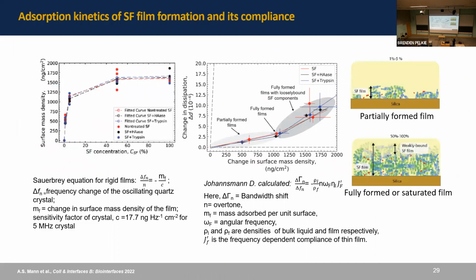So here are some results from that study. We used the Sauerbrey equation for rigid films to convert the changes in frequency to surface mass density of hydrated adsorbed mass. If we plot that as a function of bulk concentration of synovial fluid, then we get a Langmuir isotherm. We see that at low concentration of the synovial fluid, there is a partially formed thin film, which is more rigid.